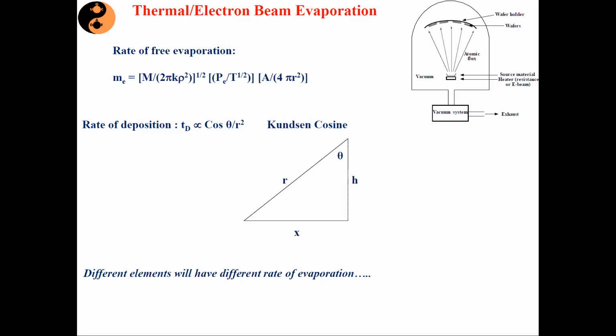So when they reach the substrate, their actual composition is not exactly as it was earlier in its original bulk form. So in your thin film, the stoichiometry of the original bulk may not be retained, and hence you will lose its original property. You can end up with an altogether different material. Therefore, this particular technique is good to grow metallic films, but not those materials like ceramics, which contain more than one element in their composition. Okay, so this is one limitation.